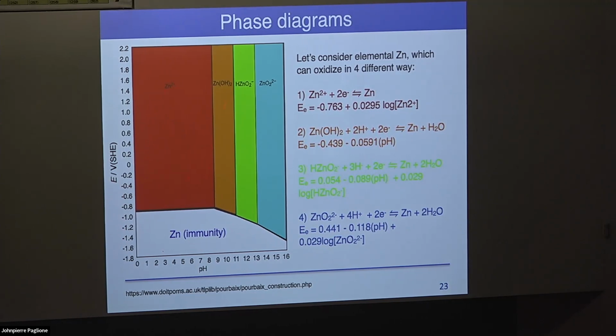But above all those lines, depending on what the different lines were, you'll have different constituents that are stable. Above the red line in this pH region, you'll have Zn2+, and in this region, you have zinc hydroxide. In this pH region, you have HZnO2-, and in this region, you have ZnO2 2-. That's all computed from the Nernst equation, which I showed you before. I didn't name it, but it's called the Nernst equation if you haven't seen it in a long time. Basically, this tells you the different regions that are stable.